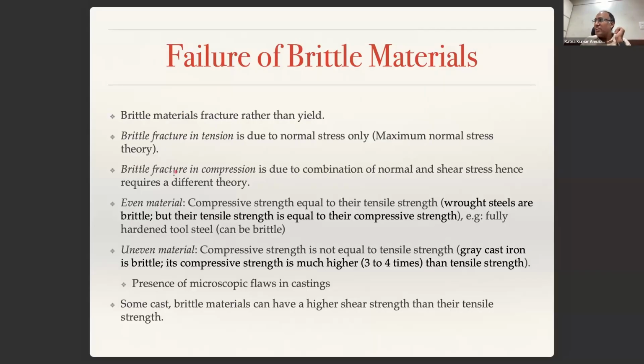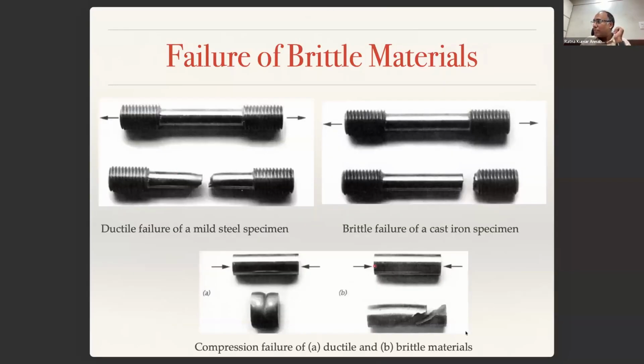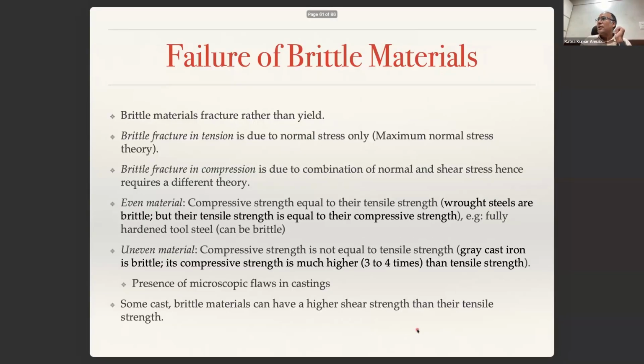Now for compression, you can see that the failure happens due to a combination of normal stress and shear stress. So brittle fracture in compression is due to a combination of normal and shear stresses, and hence it requires a different theory. You cannot use the same theory that you use for tension. So depending upon the type of loading, you have to use a different theory. When the loading is tensile, the failure can be completely governed by the normal stress theory, whereas when the loading is compressive, the failure is not governed by the normal stress alone. The effect of shear stress also comes into picture. This is something that we have to keep in mind.